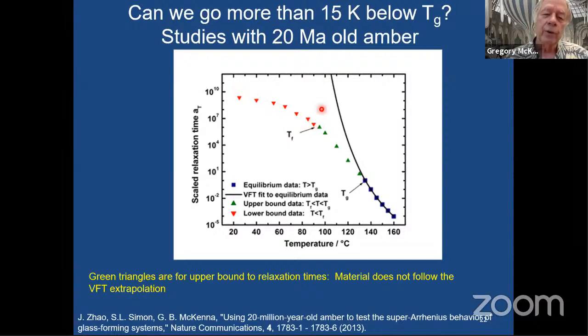But these are normal aging experiments, so they're lower bounds. And actually, it's interesting, as you cross the fictive temperature, there's sort of a little bump in the smoothness of the data. But the biggest thing is that you see that we get a very large deviation from the Vogel-Fulcher behavior. So this is 10 to the 6th maybe, and this is more than 10 to the 12th. Okay, so very, very big difference.